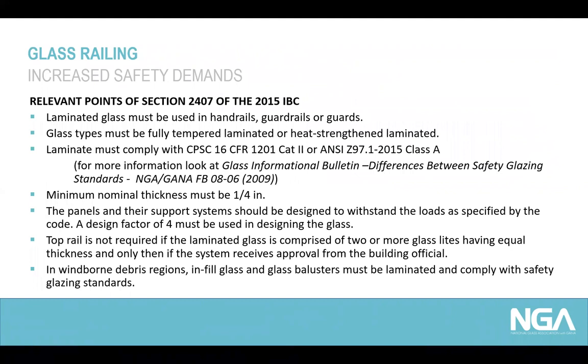And there it's required to have laminated glass for use in handrails, guardrails, and guards. Glass types must be fully tempered, laminated, or heat strengthened laminated. Laminated glass must comply with CPSC 16 CFR 1201 category 2 or ANSI Z97.1 class A. The differentiation between both of those safety glass standards is summarized in GIB FB0806 from NGA. Furthermore, there's a minimum glass thickness of 1/4 inch required. The panels and their support system should be designed to withstand the loads as specified by the code. A design factor of 4 must be used in designing the glass.